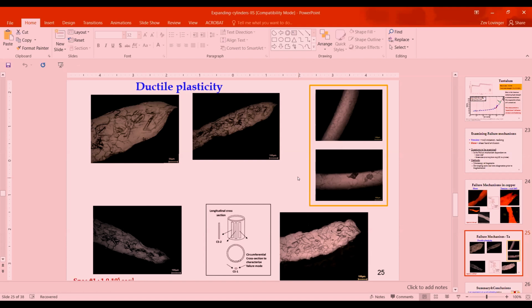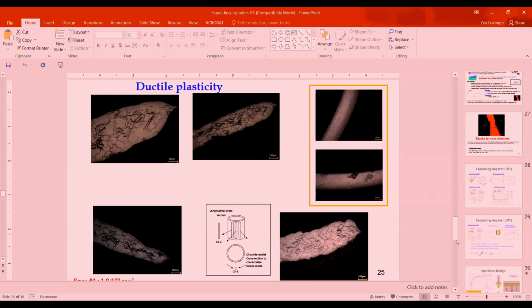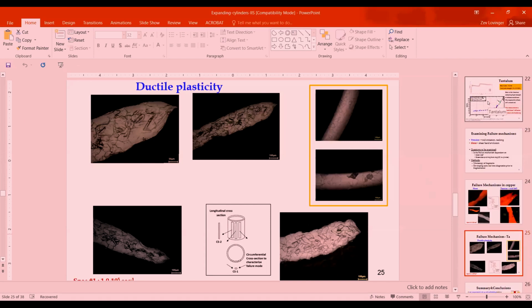So the heating, of course, the energy of the plastic strains will be there anyhow. I think when you calculate the overall temperature rise from that, it doesn't have a significant effect for most materials. Maybe not for all of them, but for most materials, this kind of heating reaching tens of percent up to about 100% of strain wouldn't be very significant. We are reaching here high strains, a failure strain of about 70%. What I showed at 0.15 was just a strain which is compared to other data in the literature. These graphs of strain rate sensitivity are usually referred to a specific plastic strain. So that's why I mentioned 0.15, but I would say that this measurement would be valid up to about 0.5.